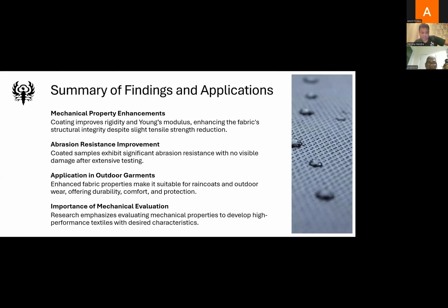So they concluded that the mechanical properties were enhanced by the coating, through the rigidity and the Young modulus, and the abrasion resistance has also been proven durable. They conclude that this kind of fabric deserves to be used for outdoor wear, because based on the evaluation, the fabric is durable as well as comfortable for clothing and protection.